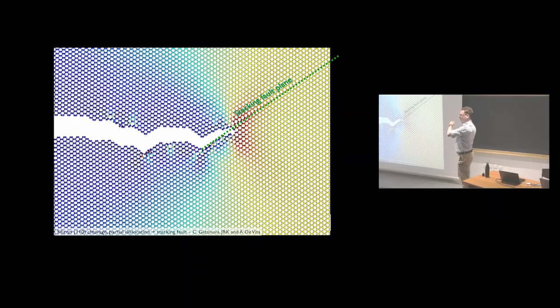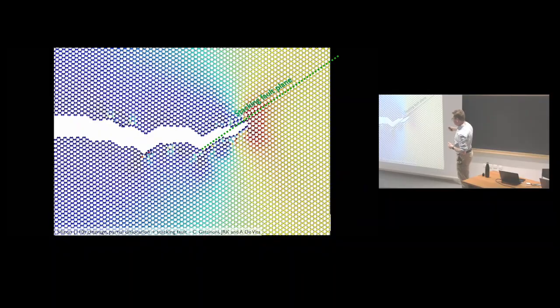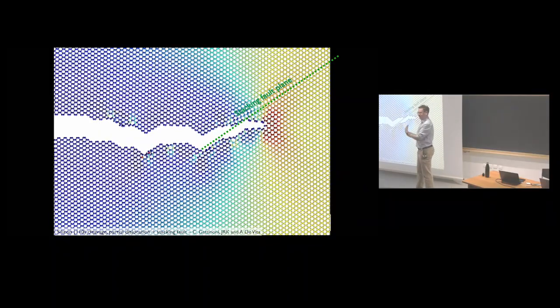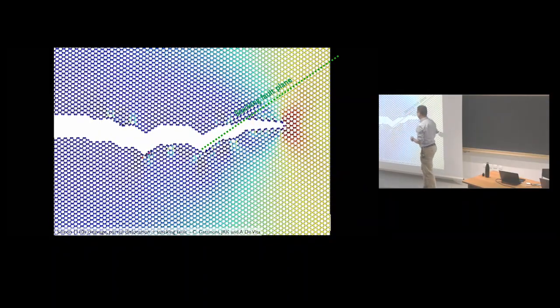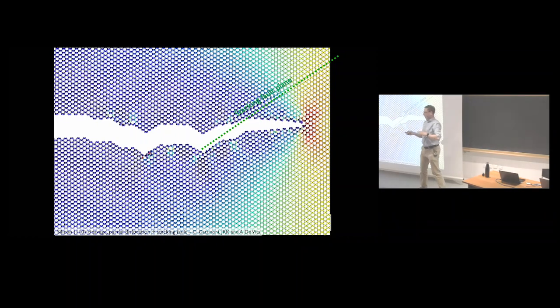This is a partial dislocation, again, like the ones I showed in FCC. So there's a stacking fault here, a weak interface within the material. So the crack takes a bit of a detour up the stacking fault. It's easier for it to propagate in that direction. And then after a while, there's too much shear. It's not favorable anymore, so it returns to the original cleavage direction.